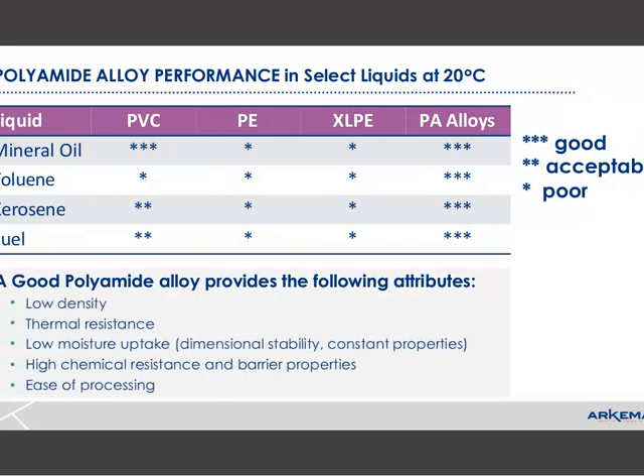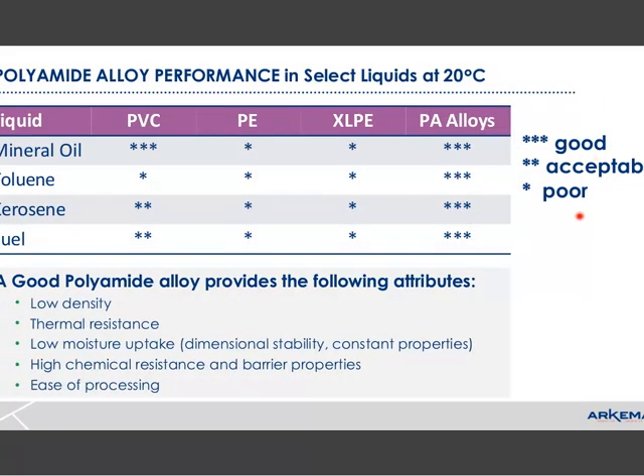One of the most important properties that you gain is chemical resistance. These polyamide polyolefin alloys have very, very good chemical resistance compared to the products that they might replace, such as crosslinked PE, PE, and PVC. They have low density, they have thermal resistance, and their chemical and barrier properties are exceptional. This is where the nylon actually becomes very dominant in its properties, whereas the presence of the polyolefin reduces its moisture uptake. The other characteristic of these products is that they're very easy to process.